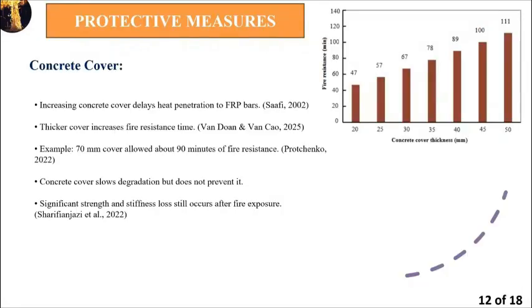So now we will move to protective measures, starting with concrete cover, some kind of improvement or solution. Actually, one of the main ways to protect FRP reinforcement from fire is by increasing the concrete cover. I mean, the concrete acts as a thermal barrier between the fire and the FRP bars. So when the concrete cover is thicker, it slows down the heat transfer to the reinforcement, and this will delay the temperature rise in the FRP bars and postpone reaching the critical glass transition temperature.